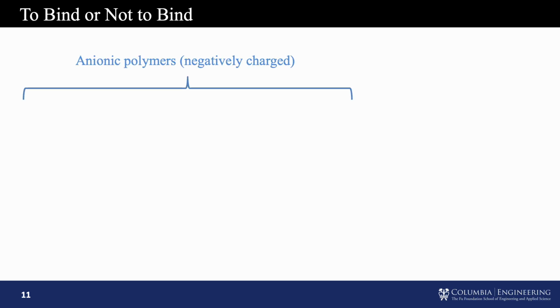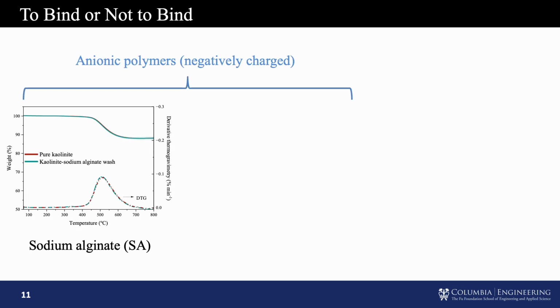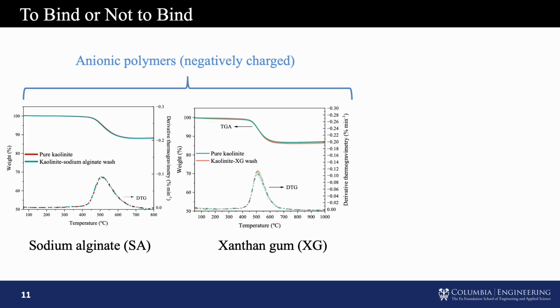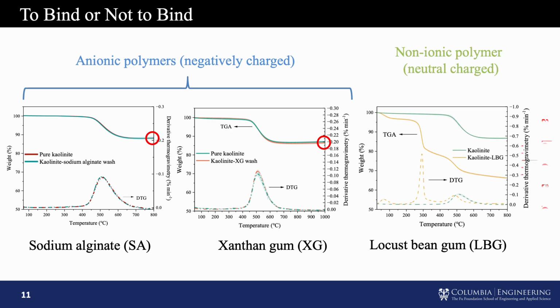So we know the anionic polymers, the negatively charged polymers like sodium alginate and xanthan gum, are not binding. It's pretty easy to understand because clay is also negatively charged, and these polymers are also negatively charged. They have strong electrostatic repulsion between these polymers and clay. A very strong binding affinity between clay and polymer was found for locust bean gum because it is non-ionic and also pretty hydrophobic. So there will be a very strong hydrophobic interaction between clay and polymer. Eventually, the locust bean gum binds to clay, while xanthan and sodium alginate do not bind to clay.